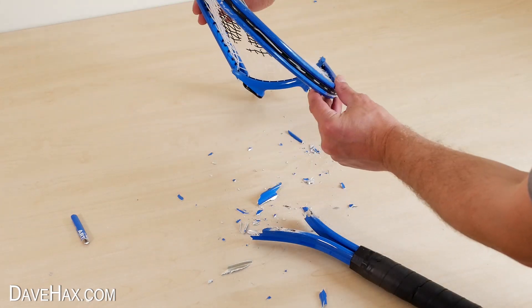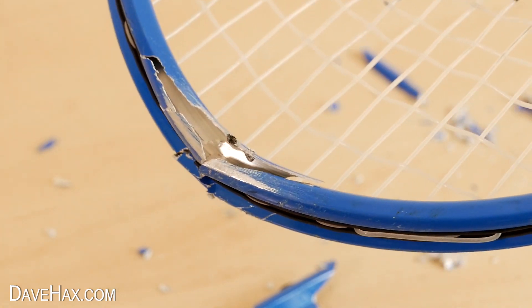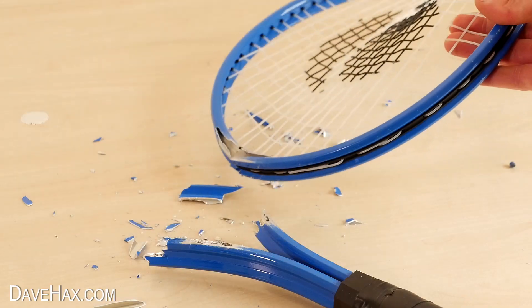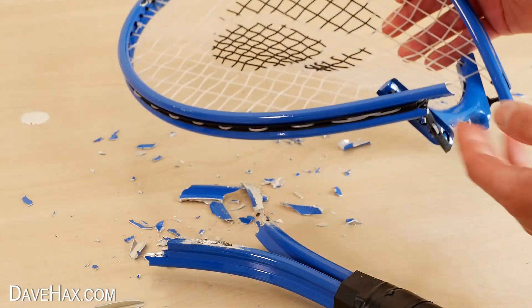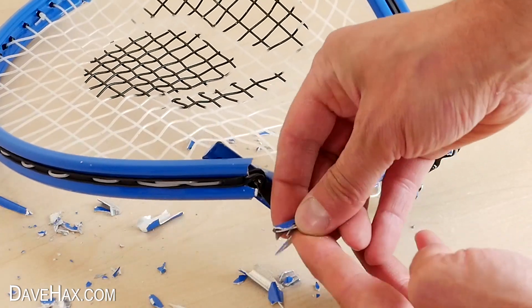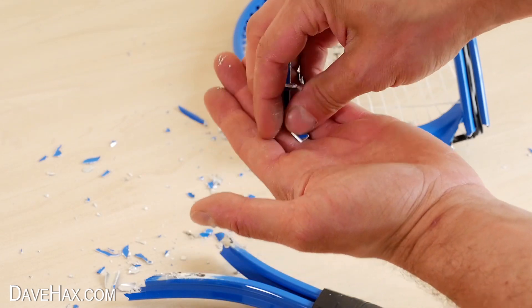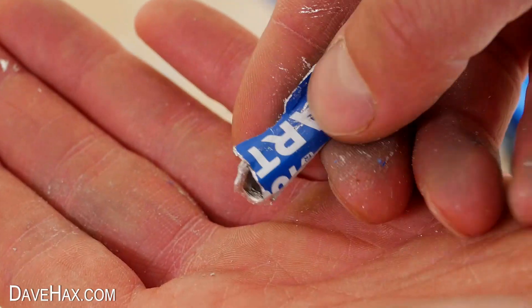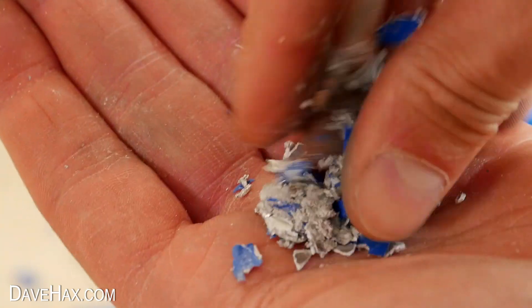So I picked it up to have a look. The frame is just completely disintegrated around where we applied the gallium. I think the plastic strip around the frame is the only thing holding it together. And if I try to break it up, you can see how weak it is — these ends just snap off and crumble apart. These bits of frame that just broke off have lost any strength and break up easily in my fingers.